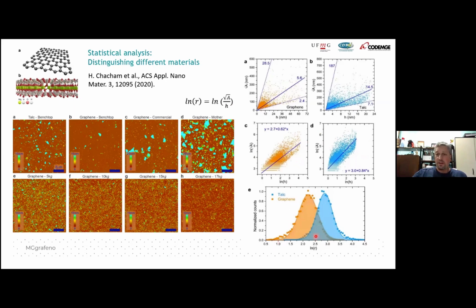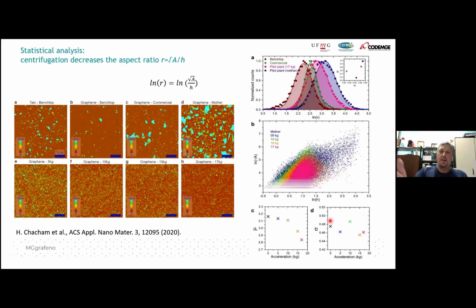If we take the logarithm of these distributions, we have very accurate information about our system. This is explained in this paper. And we see here that we make these samples with exactly the same procedure, and they are different, and we can see that here. If you just look at the data, you don't see much. It's hard to extract the information, but we can see it here.